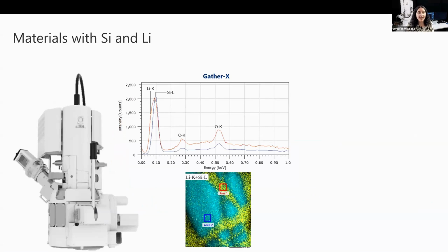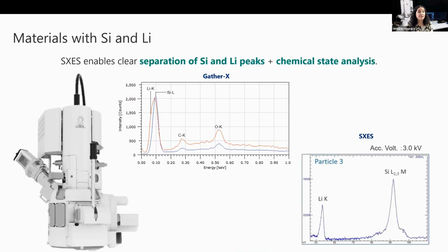And if we return to that Gather-X EDS spectrum that I showed earlier of lithium and silicon in an all-solid state lithium-ion battery, where we needed to rely on peak deconvolution to separate the lithium K and silicon L lines, the SXES is fully able to resolve those peaks, making it a powerful technique in battery research, for example, for both detecting lithium and for analyzing the chemical state of the silicon anode.